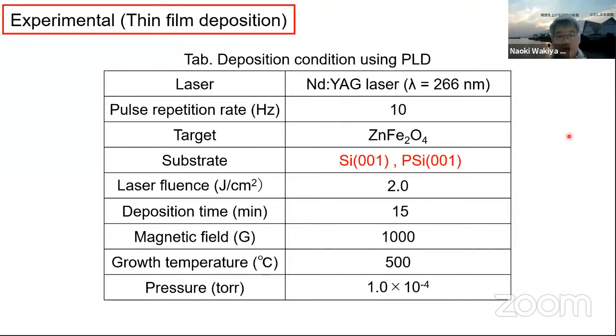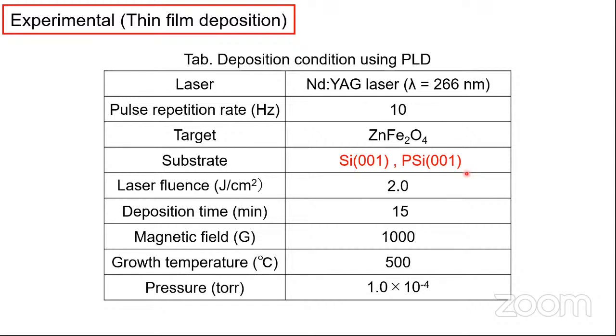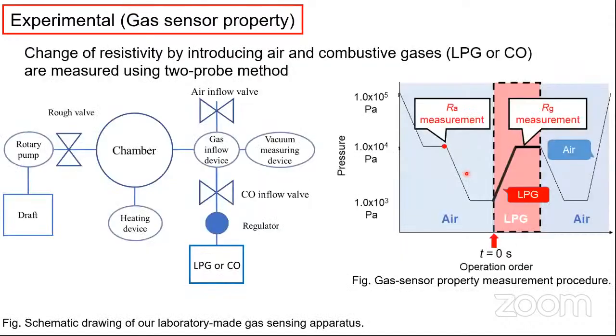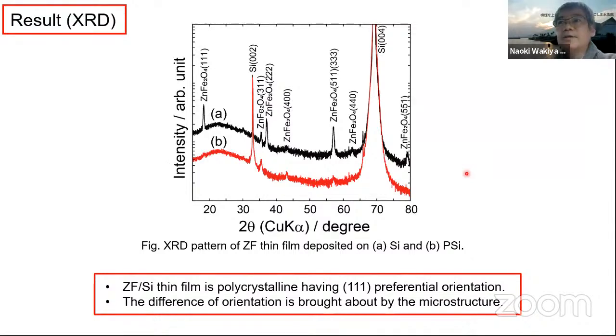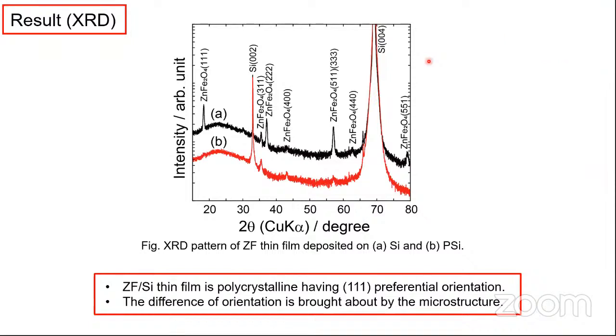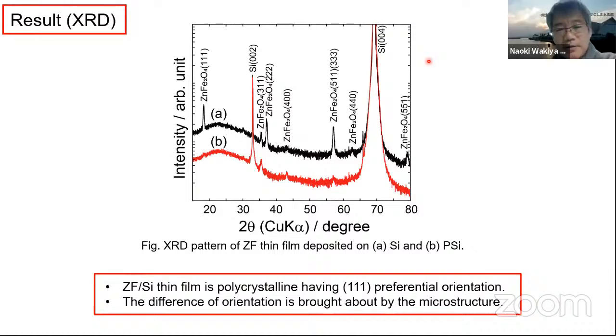Yeah, zinc ferrite. Correct, this one. So, you mean the experimental condition? No, they are asking whether it is possible to do Rietveld refinement XRD. You mean Rietveld analysis? Yes. Okay. This is a thin film sample, and Rietveld analysis is for powder samples. So, can we do the Rietveld refinement for zinc ferrite? I think it is very difficult to carry out Rietveld analysis for thin film because there is a preferential orientation.